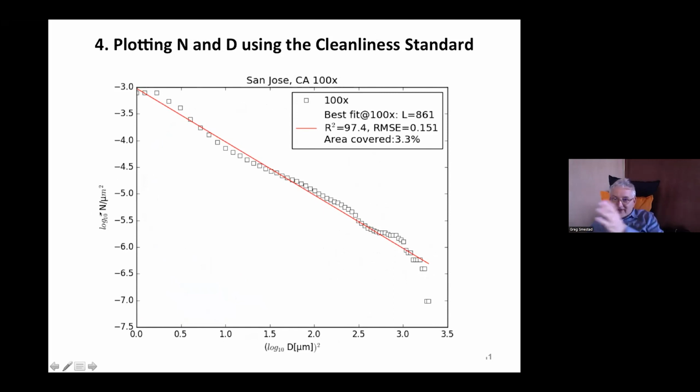So we have to add up all the different sizes as a function of the particle size. The previous plot comes out fairly good on a log plot, so that, as Leo has done here, we can show that this is characterized by a single number, 861. And for the area coverage, we can also say that 3.3% of the surface is covered by particles.